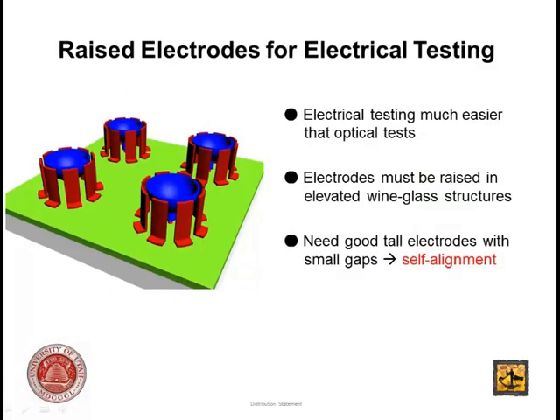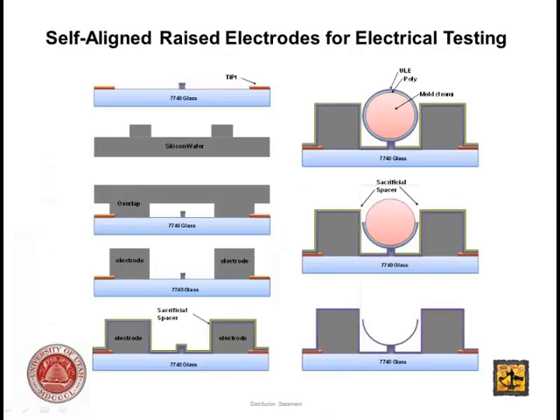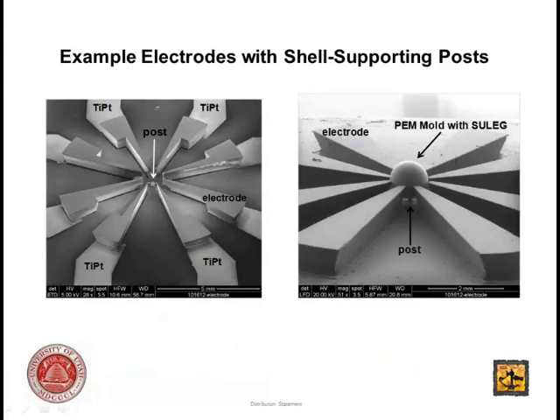But what we're trying to do in the future is to incorporate electrodes for the shells so we can drive them electrically. To do that, we also developed this process that makes elevated electrodes. So you have the post plus an elevated electrode, and then it puts a sacrificial layer on top of the whole thing. And then we can bond this structure and remove the sacrificial layer. So everything is self-aligned, and it leaves a gap at the end. This is work in progress.